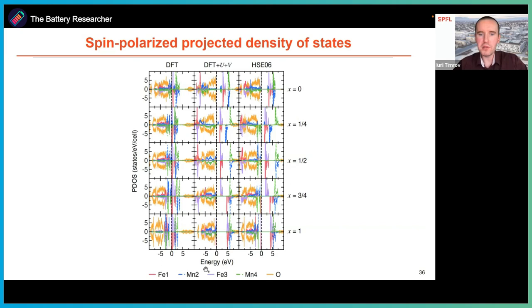But what I would like to pass as the take home message is that DFT plus U plus V and hybrid functional show very, very similar qualitative behavior, so how electronic states move as we lithiate the material. They show very similar trends. And this means that instead of using computationally very expensive hybrid functionals, we can use less computationally expensive DFT plus U plus V. But we also saw before that voltages are more accurate than with hybrids. So that's another reason why DFT plus U plus V seems to be a very attractive method.